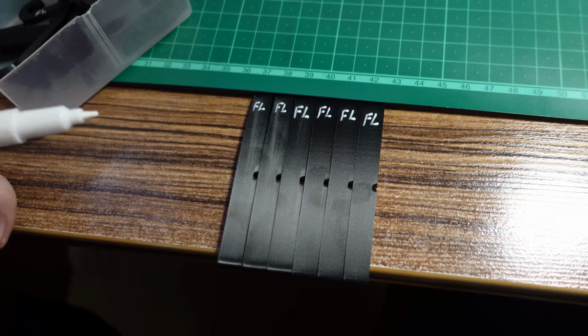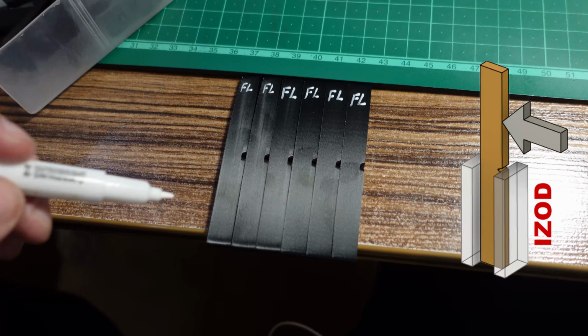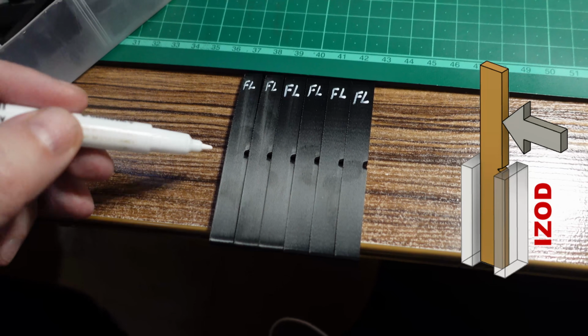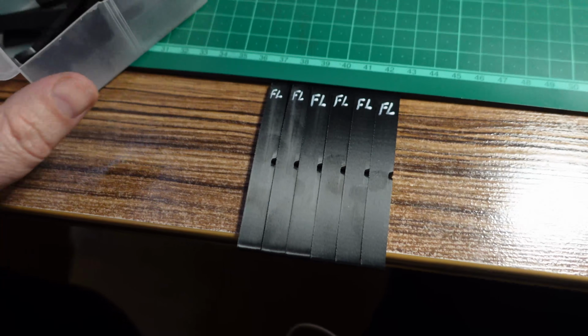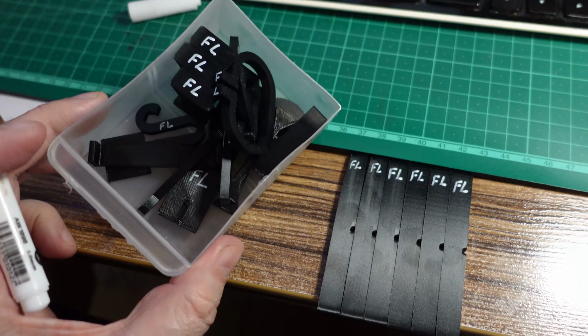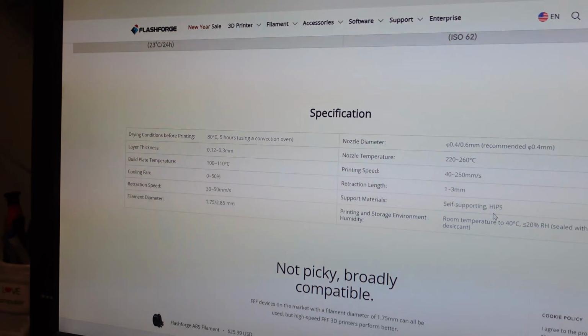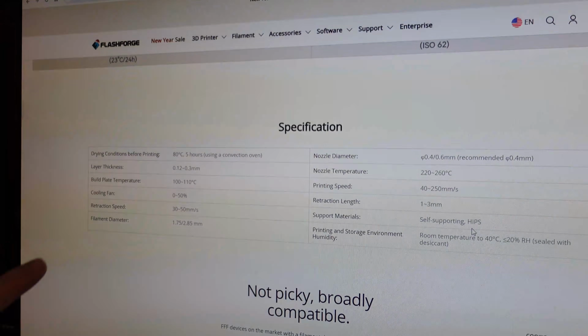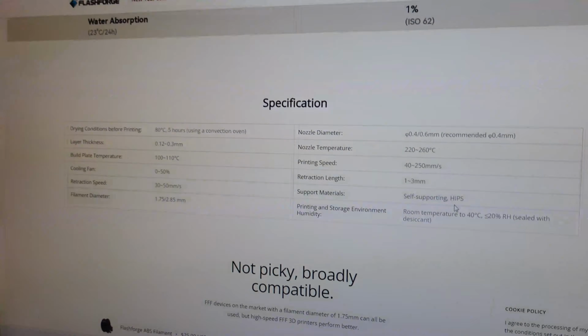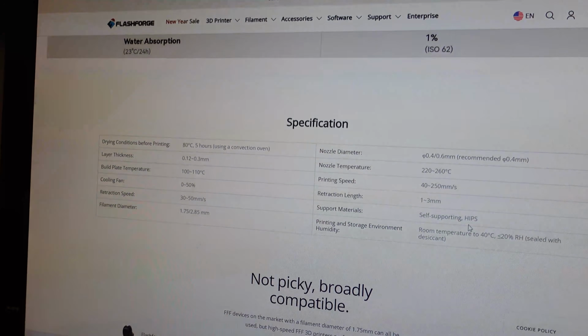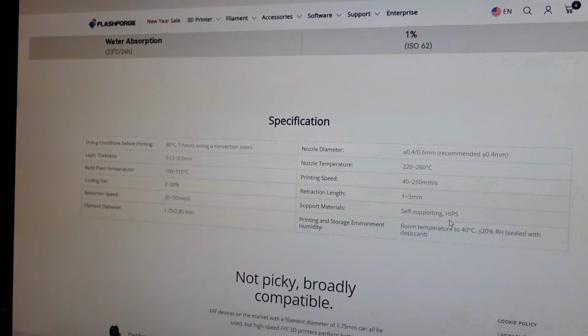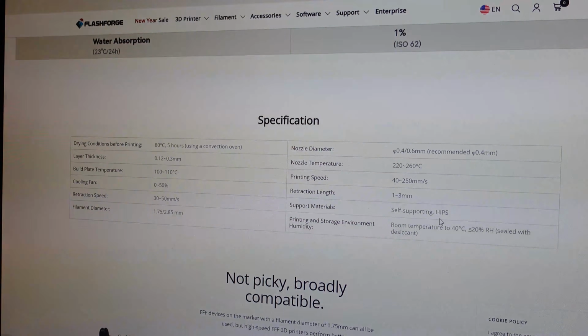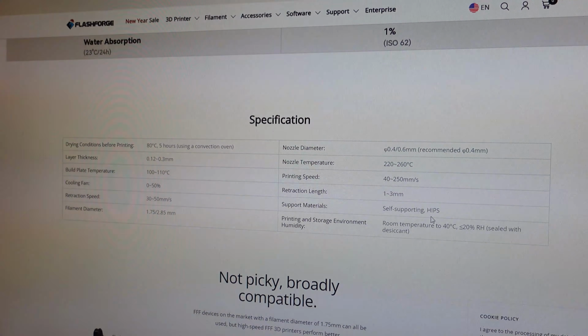So this means for the Izod testing they'll be fine because they'll be held on the lower part and the cross section is unchanged. All other objects are perfectly straight, no warping. Now maybe it is partly my mistake because officially they recommend 100-110 degrees Celsius on the build plate and I use 90, which is the default for the generic ABS. But I'm using the same settings for all 8 ABS filaments.